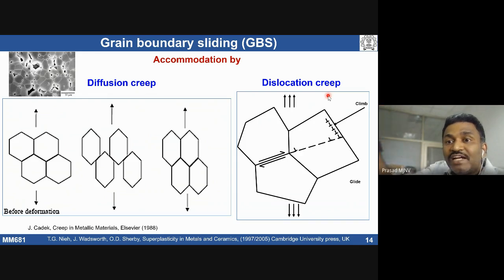Okay, so that's where your temperature effect also comes into the picture. Even if it's a fine grain size, low temperature versus high temperature is the issue. So we do see low ductility regimes in steels. When you deform material at low or intermediate temperatures, grain boundary sliding is taking place, but there's no accommodation. That can lead to cracking and failure of the component.